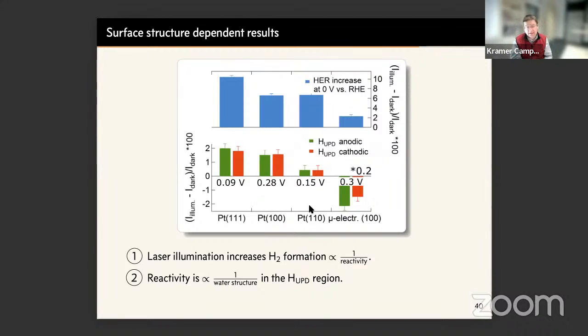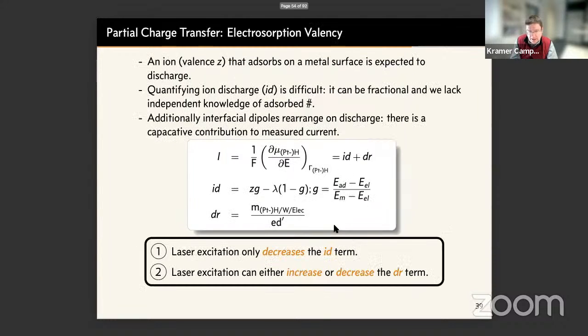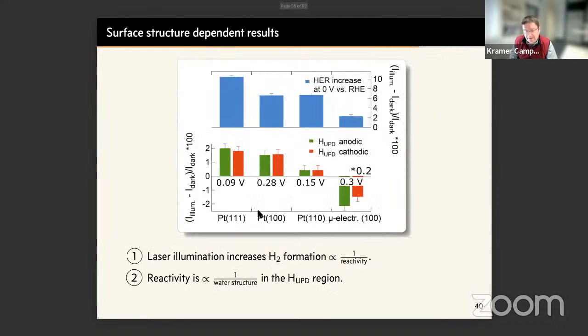It is also clear, right, that this is this point number 2. If you think about now this reduction of this sign, the sort of logic that I described on the previous slide, what this suggests is that in the case of platinum 111, there is a kind of overcompensation of the interfacial solvation layer to this charge transfer, which does not exist for the case of the microelectrode. And we can discuss that. And this effect appears to correlate with reactivity. So it seems logical to suggest that one might need a kind of Goldilocks configuration of solvent molecules to produce a more reactive surface.